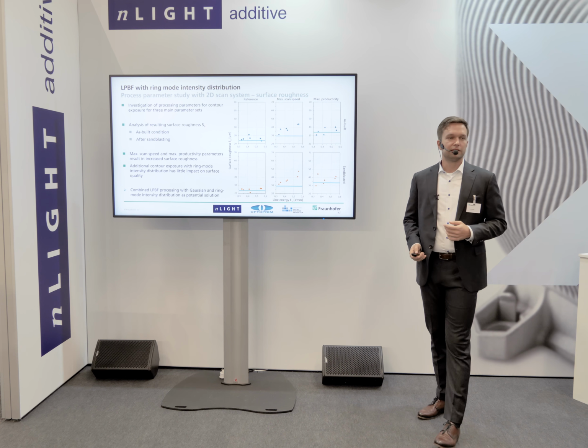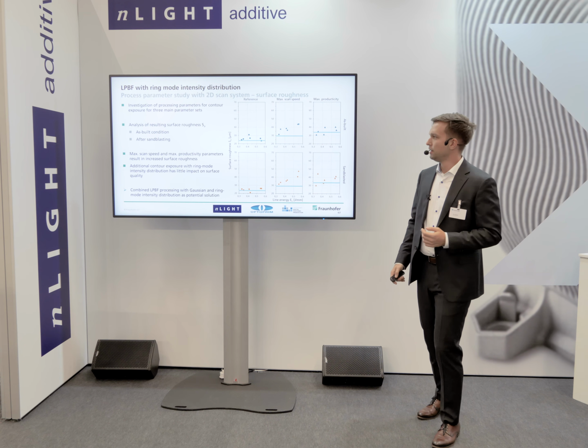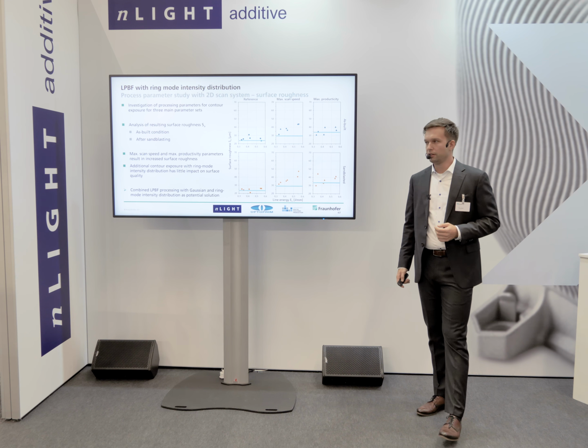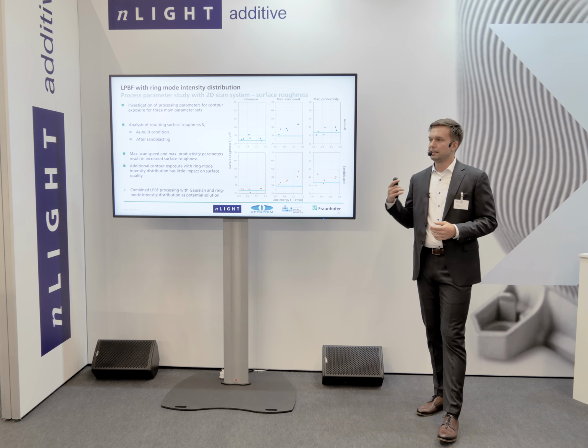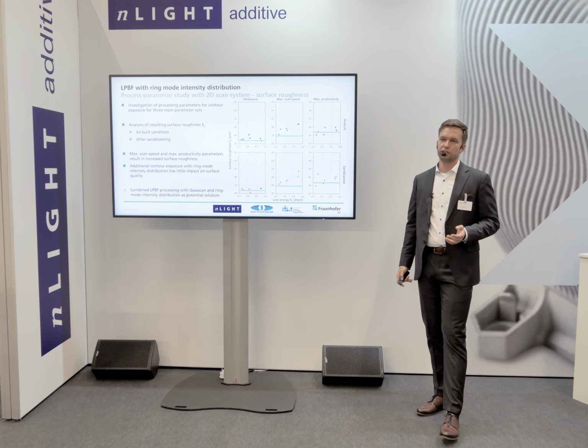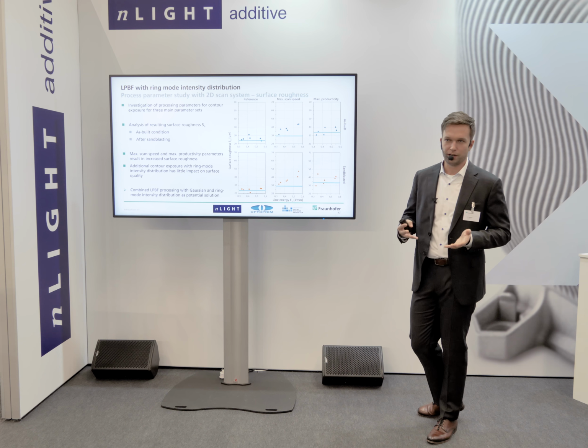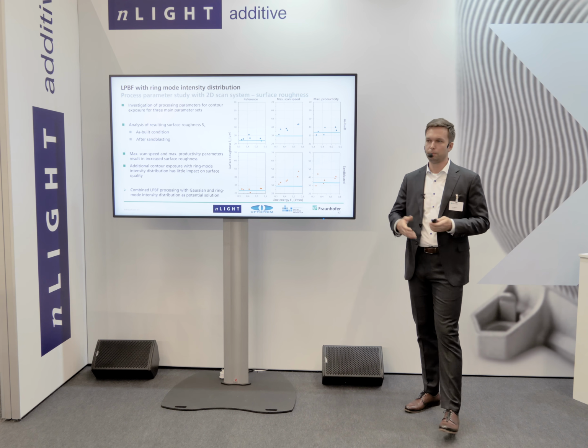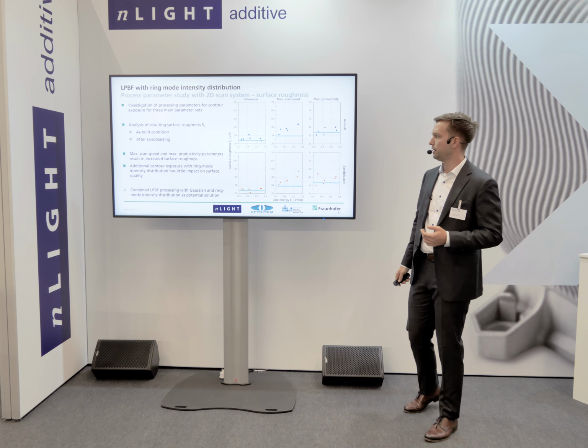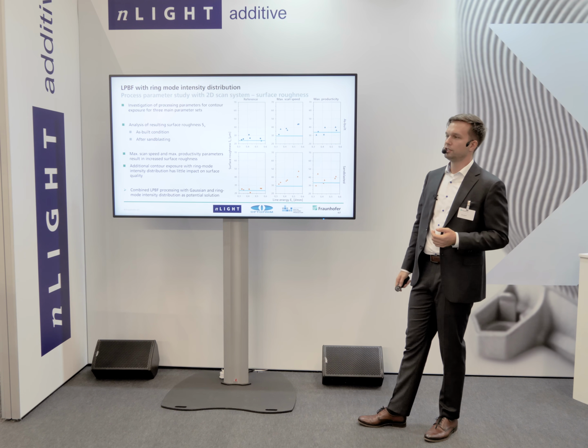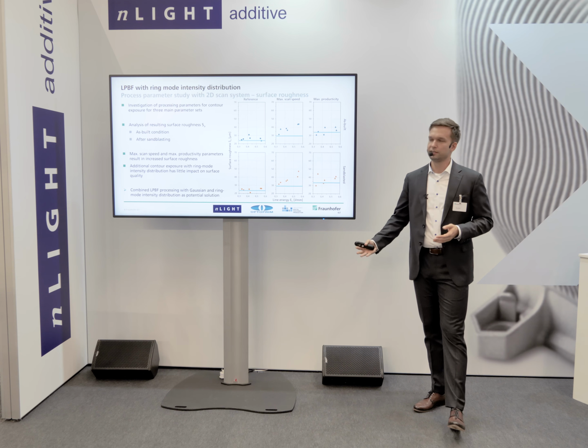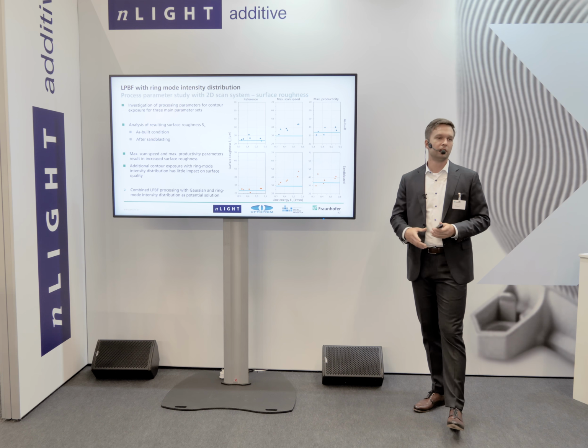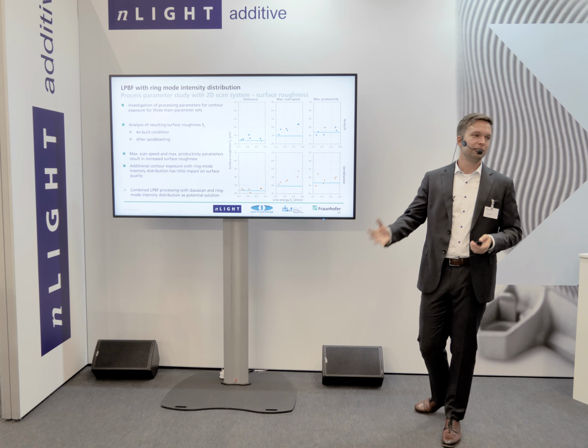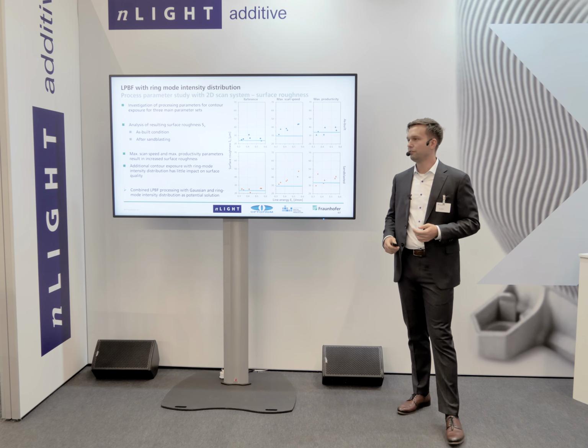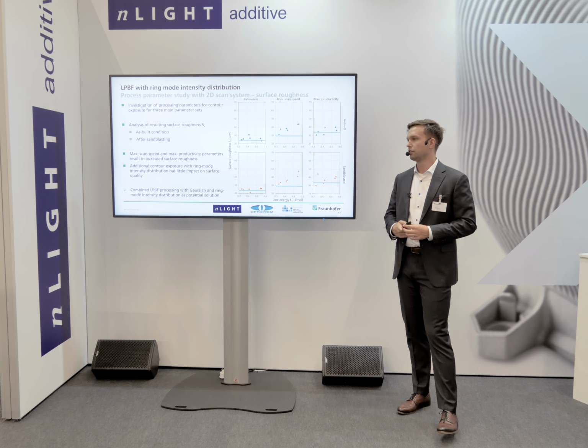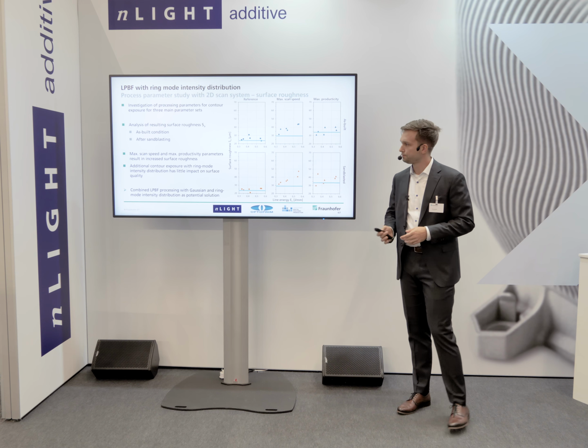Additionally, we investigated contour accuracy and surface roughness. Here we found that in general the ring yields a slightly higher surface roughness than single mode Gaussian, which also makes sense. The melt pool is wider, and therefore you probably have a lot more powder particles stuck to the part, which then was our motivation to say, okay, adapted processing strategies with ring and single mode make a lot of sense, because you have the high productivity for the edge of the part and can then have also the high surface quality for the Gaussian during contour exposure.